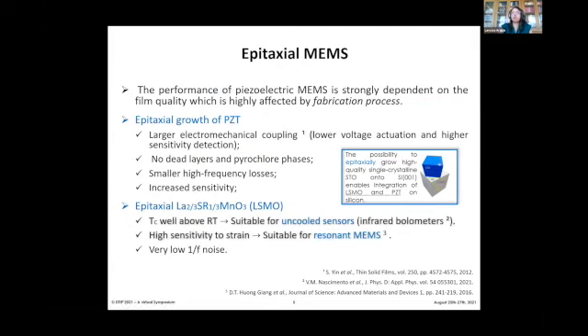So why we want to do this epitaxially, although we know all the background, the drawbacks, in fact, of using epitaxial materials, we're going to have strain attached to this. But the fact is that when you use epitaxial oxides, such as LSMO, it has a very high sensitivity to strain. Hence, it's really suitable for resonant MEMS. And also, its Curie temperature is well above room temperature. So it's really suitable for uncooled sensors. So we can use it without the necessity to work in a low temperature environment.